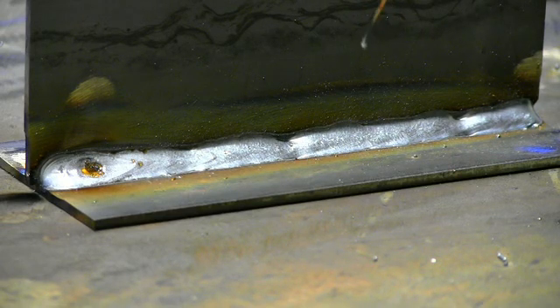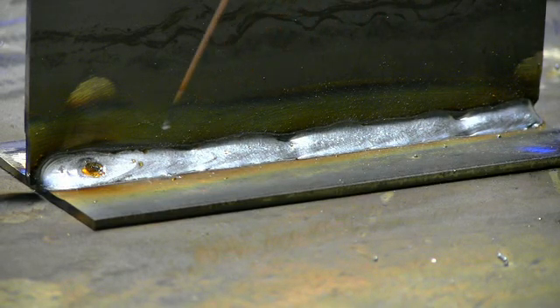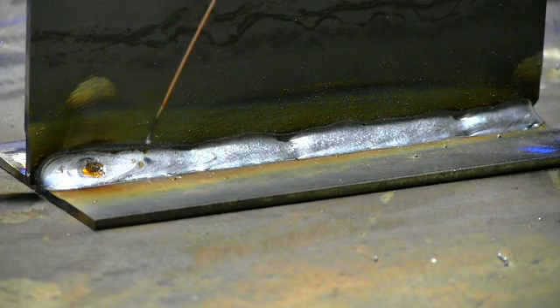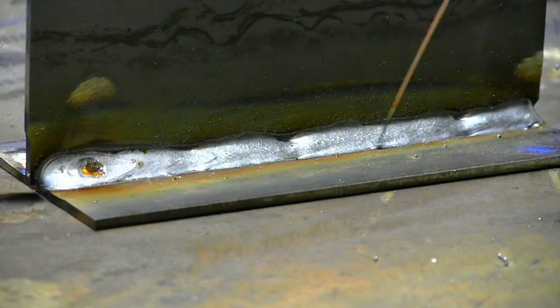Not to mention it puts a great deal more heat input per inch into your weld, so you have to keep that in mind as well. So the higher the voltage you go, the less spatter you get, but you also start having a harder time controlling the weld profile.